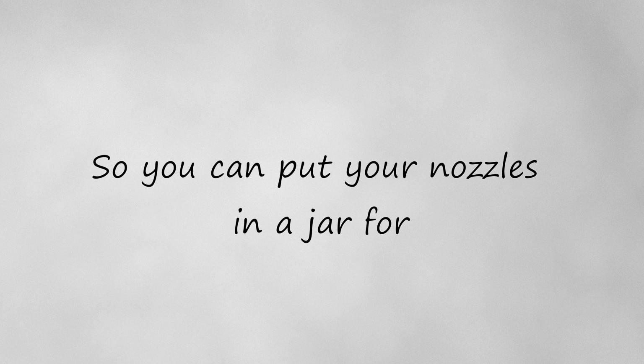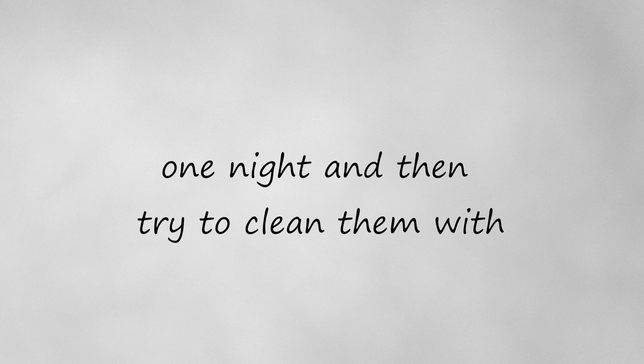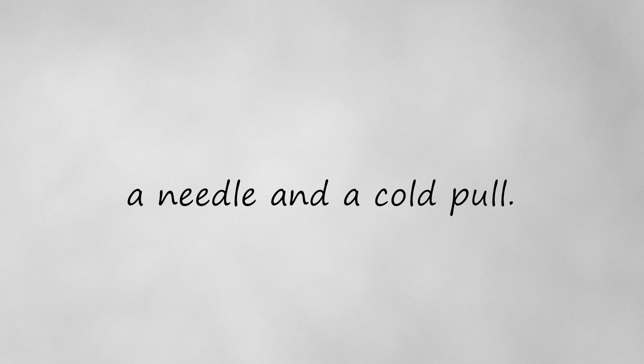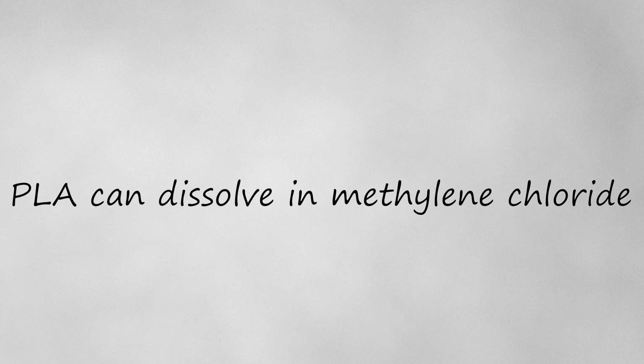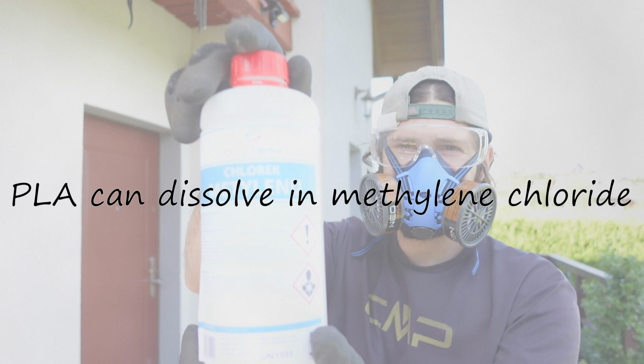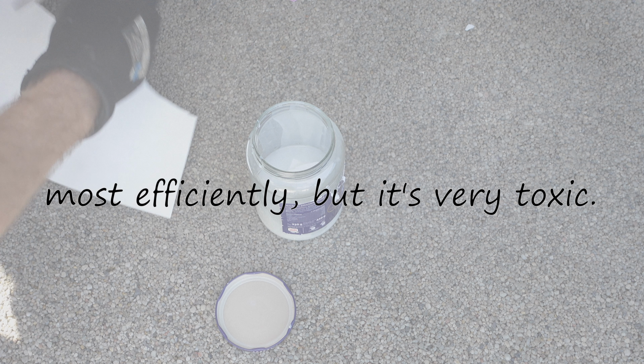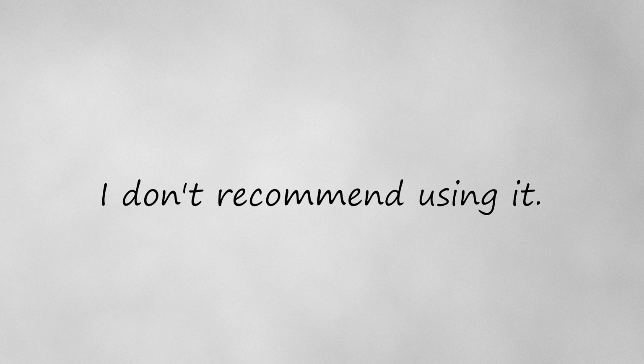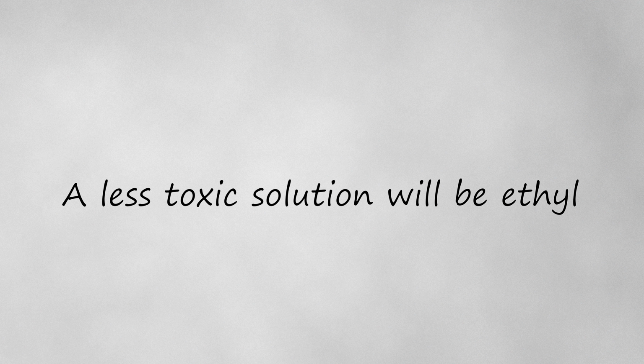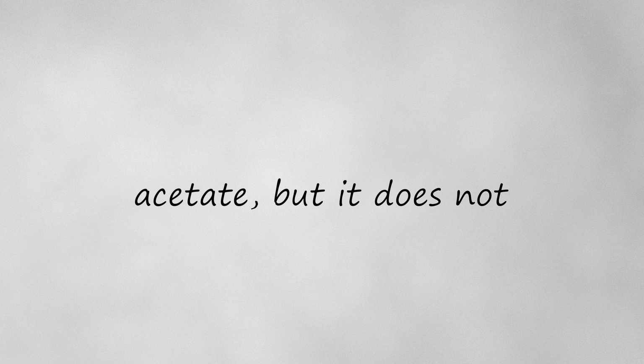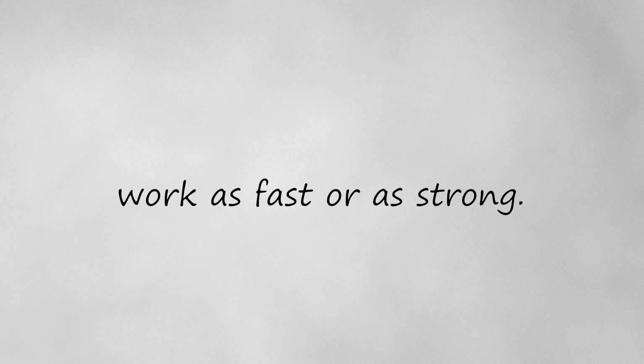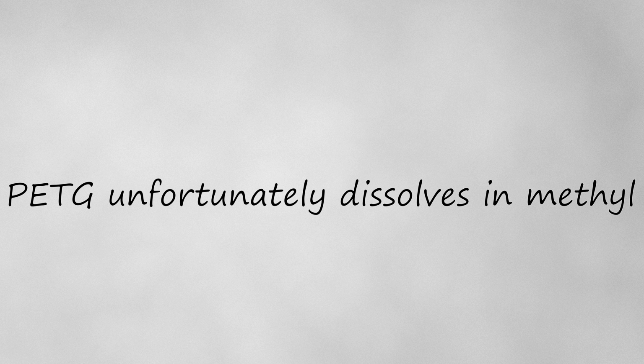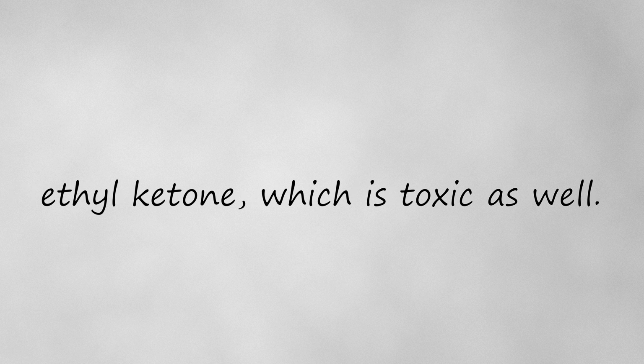For example, ASA and ABS dissolve in acetone. So you can put your nozzles in a jar for one night and then try to clean them with a needle and a cold pull. PLA can dissolve in methylene chloride most efficiently, but it's very toxic. I don't recommend using it. A less toxic solution would be ethyl acetate, but it does not work as fast or as strong. PETG unfortunately dissolves in methyl ethyl ketone, which is toxic as well.